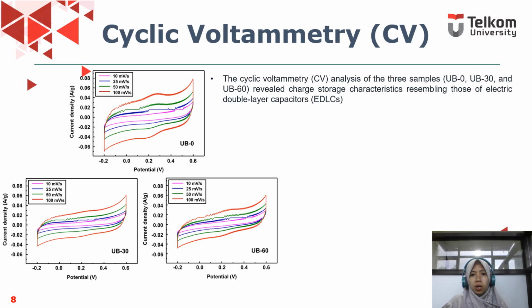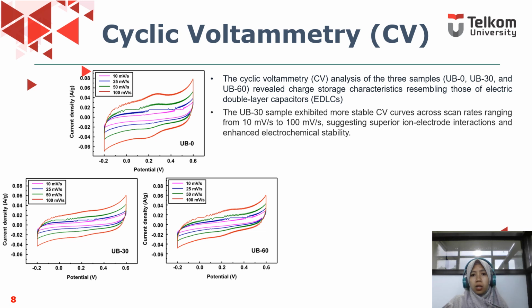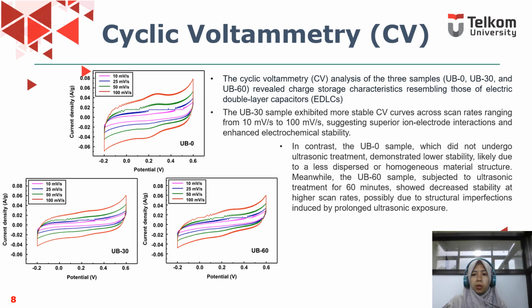The figure presents the CV curve of supercapacitor electrodes fabricated from three samples. The cyclic voltammetry CV analysis of three samples revealed charge storage characteristic resembling those of electric double-layer capacitor. The UB-30 sample exhibit a more stable CV curve, scan rates ranging from 10 until 100 millivolt per second, suggesting superior ion-electrode interaction and enhanced electrochemical stability.